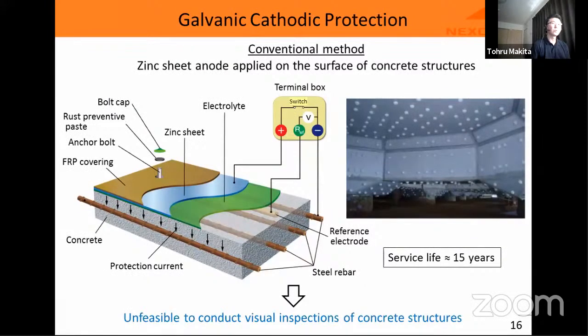Another method used to address chloride-related damage of concrete structures is cathodic protection. There are two different types of cathodic protection system. One is impressed current cathodic protection system, and another is galvanic cathodic protection system. Since more maintenance effort is necessary for the impressed current cathodic protection system to be operated, galvanic cathodic protection system is preferred in our maintenance. So conventional zinc sheet anode is applied on the surface of concrete structures in galvanic cathodic protection system.